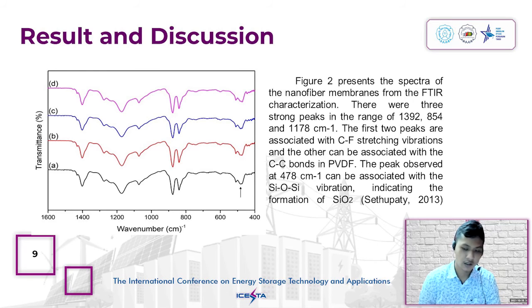Second, FTIR characterization. Figure 2 presents the spectra of the nanofiber membranes from the FTIR characterization. There were three strong peaks. The first two peaks are associated with CF stretching vibration and the other can be associated with the CC bond in PVDF. The peak observed at 478 centimeter can be associated with the Si-O-Si vibration, indicating the formation of SiO2.